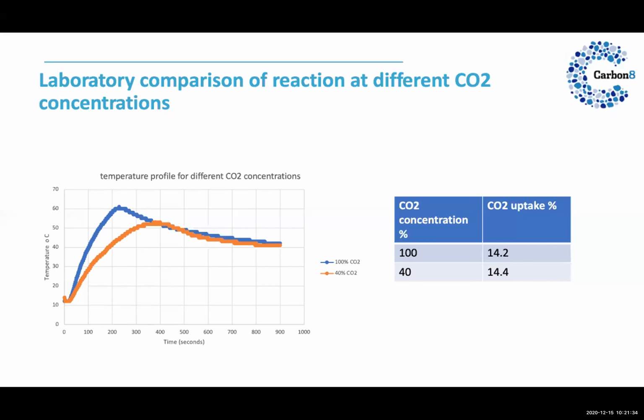The other thing that we found is that you can blind the grains if you're using 100% CO2. The reaction is so quick, as you can see from the exotherm there, that you get a zone of carbonate around your grains, which prevents the diffusion of the CO2 into the grain. So overall, the reaction can be more efficient at lower concentrations of CO2.